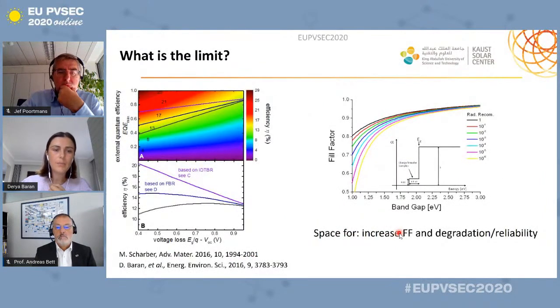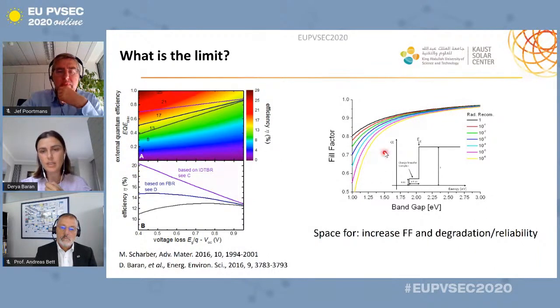So with that, I'd like to ask, what is the limit where it can go? Again, coming back to this 20%, now it doesn't seem that far. And what we can push is the fill factor, and the answer to that fill factor can be found in the radiative recombination. So if we can design new materials to increase the radiative recombination, we can actually get up to 80-85% for these 1.7 eV systems.